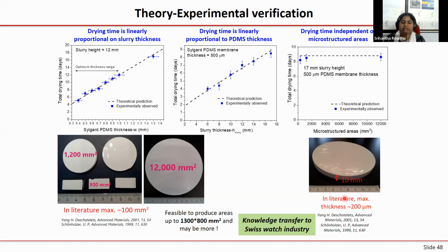That is the first implication. The second thing is that people were able to pattern surface areas of maximum 100 mm square. But with this approach, because it is independent of the base area, I patterned 12,000 mm square, which is way higher than what the literature has made. So that means upscaling is actually possible. A lot of surfaces can be patterned by this methodology. And we did the knowledge transfer to a Swiss watch company.